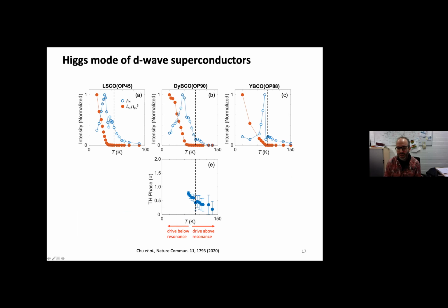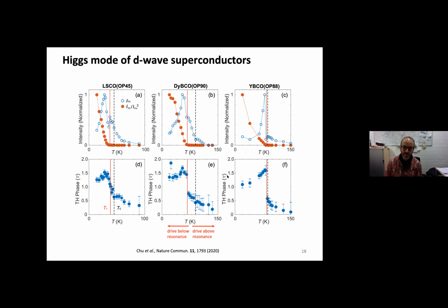But then a big surprise happened when we tuned the temperature even lower, because then we found at temperatures far below TC a very prominent phase jump in this material. And this is a phase jump that is happening in all of these materials. And there are two important observations of this phase jump. One, if you go to the unnormalized data, this phase jump is happening at this shoulder or at this notch of this THG in this system. So it looks like this is very close to some kind of an anti-resonance.